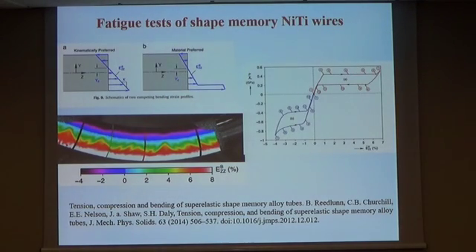But the problem is that all of them apply very complex stress state distributions, inhomogeneous transformation fronts, and also a high rotating speed. So the idea is to look for a better procedure to analyze the intrinsic behavior of the material, to try to develop a tensile test for superelastic cycling.